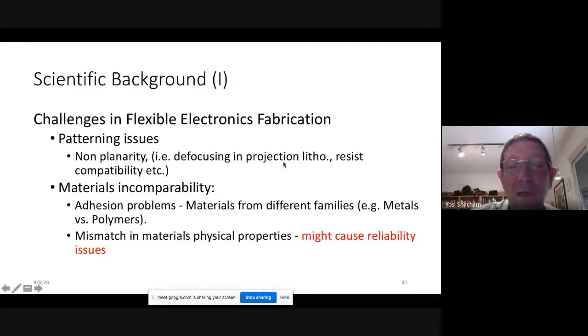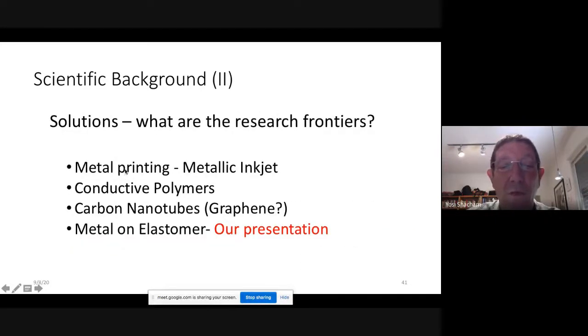The problem is that all the lithography is using polymers, and your substrate is also a polymer. It's also very difficult to make the compatibility so that one material will not affect the other material. So there's a lot of patterning issues in flexible sensors. It's very complicated to do the patterning. It's very difficult to do polymer substrate and polymer lithography. You have material problems, materials from different families, like metal on polymers, and you have a big mismatch in material physical properties that might cause very big reliability issues.